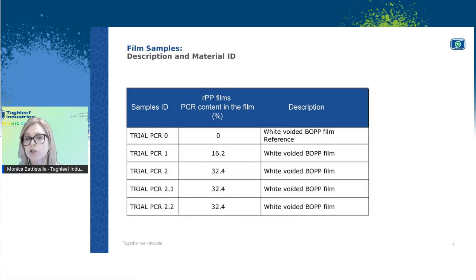So what we could achieve in terms of content of mechanically recycled PP, as you can see here, starting from the reference film, which in this case is shown with zero recycled content. So we could progress step by step by adding the recycled resin into the film, and we were able to achieve 16.2%. And then once all the parameters in the extrusion line were stable, we were able to go up, reaching 32.4%. So as a first trial, it was indeed showing very, very good results, excellent results. And I have to confirm and inform you that the same target could be achieved even last year on the occasion of the second trials.